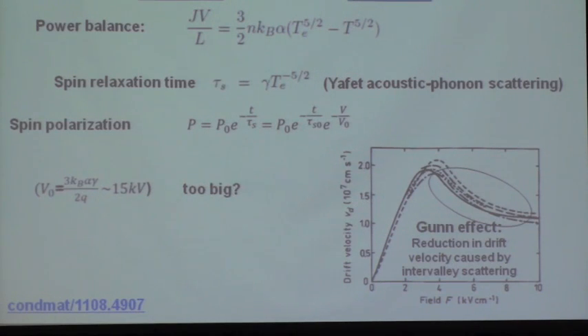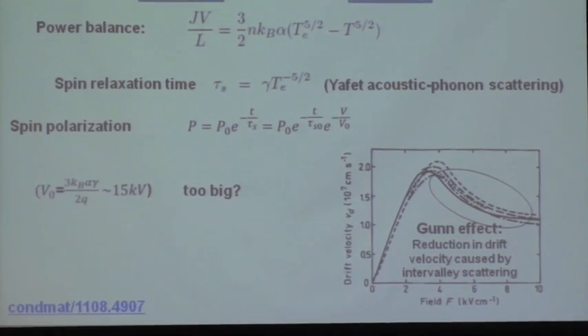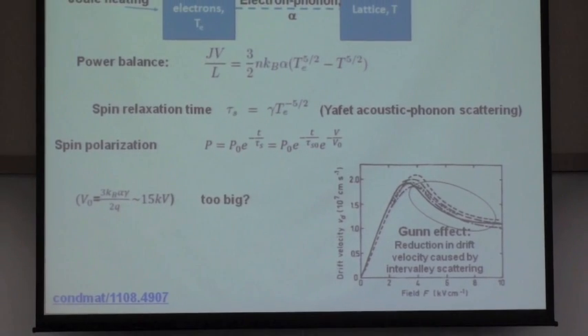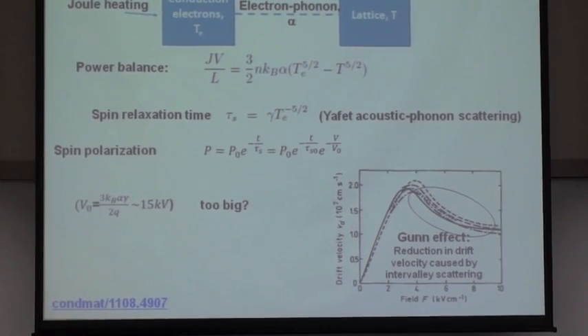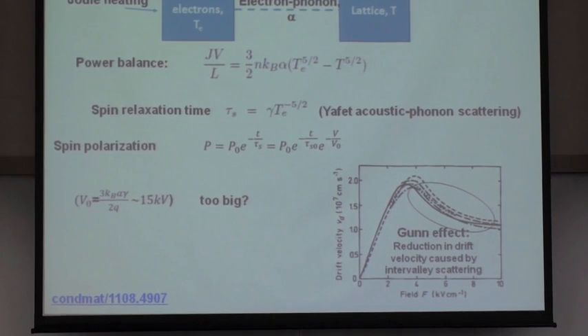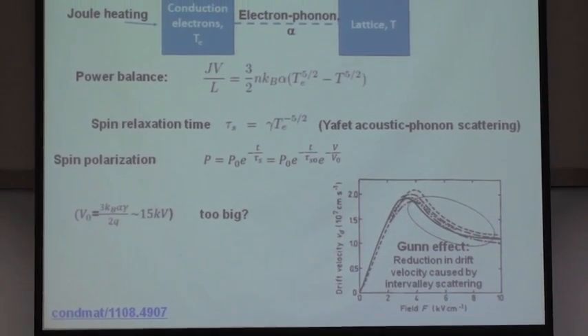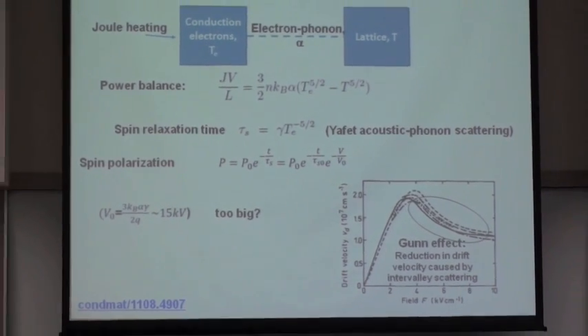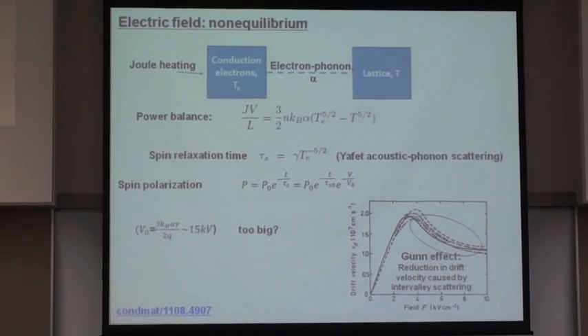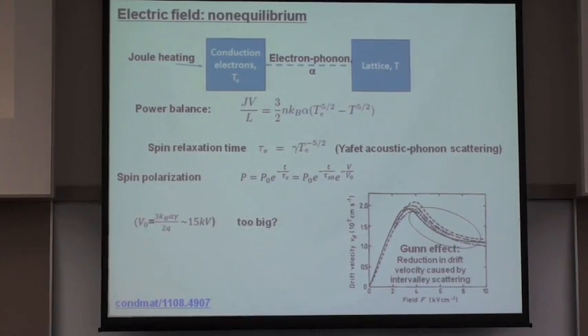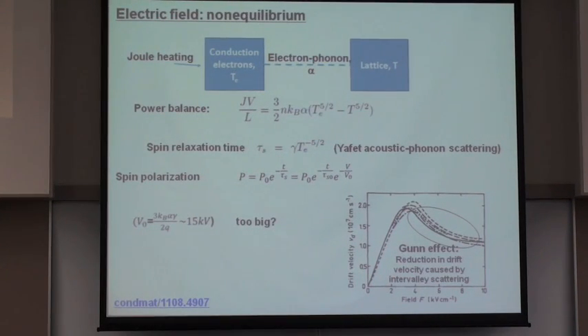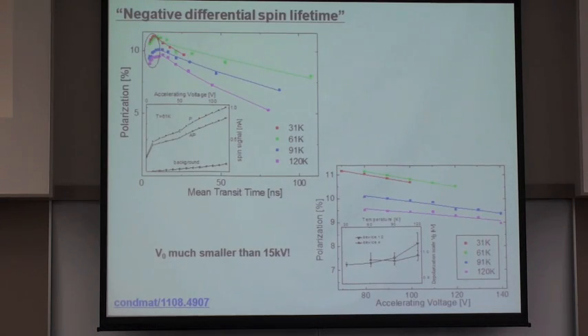So the question is, can we actually measure this? Well, with this heuristic and overly simplistic model, which takes into account only acoustic phonon scattering that occurs within the same conduction band valley, we would calculate a voltage scale of 15,000 volts. So previously I showed you this linear, static response under application of several hundred volts. I think it was something like 600 volts. So the question is, if we apply even stronger electric fields at higher voltages, would we actually see this negative differential spin lifetime? And the fact is we do.